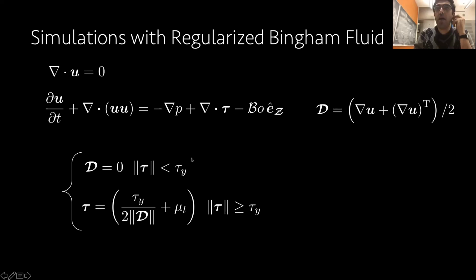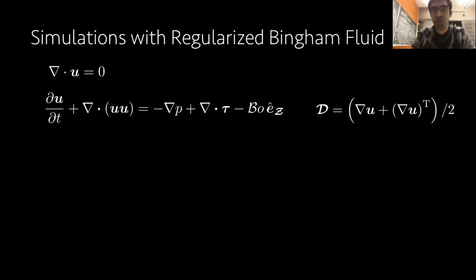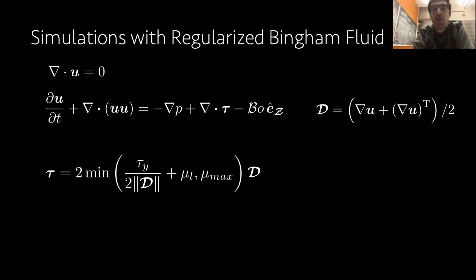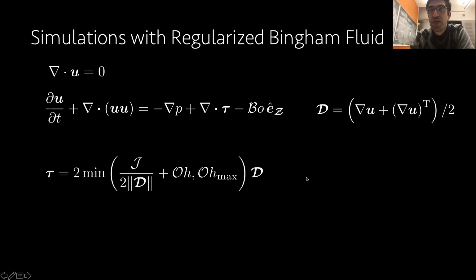My strain rate should go to 0 below the yield stress, and should look like a Bingham plastic above the yield stress. But we didn't really solve for the exact yield surfaces. So we used the regularized version of the Bingham model, which looks like this. In dimensional form, I basically use a maximum viscosity. So there's another viscosity in my equations that prevents the overshoot of viscosity. There's a large viscosity in non-dimensional form. My regularization looks like this.